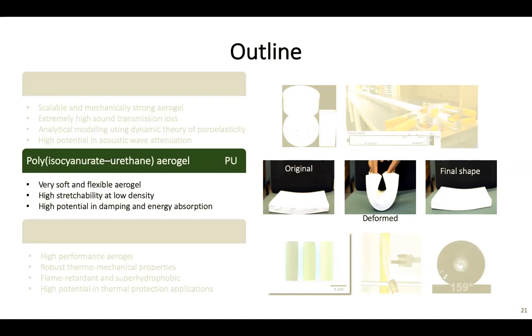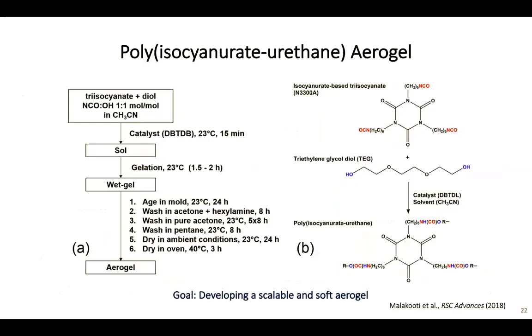This material was synthesized based on a commercialized monomer and a diol. The diol that we used is TEG. The choice of diol can help you to tune the mechanical properties of the aerogel. Like we can use different diols, different lengths for the diols.